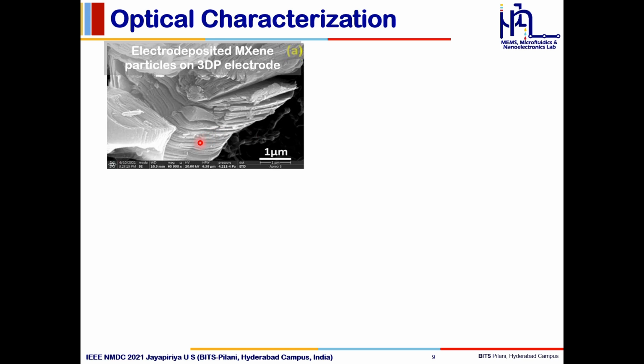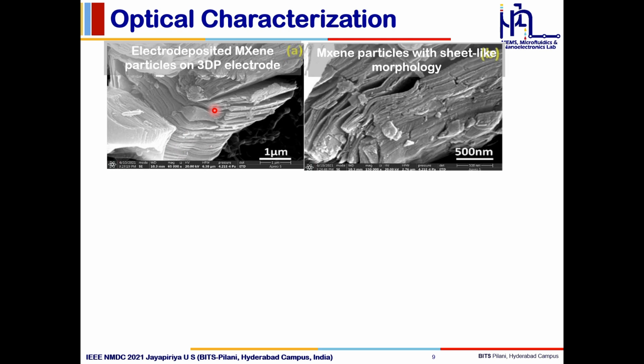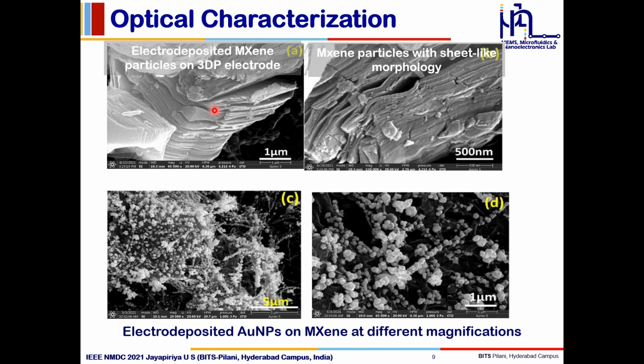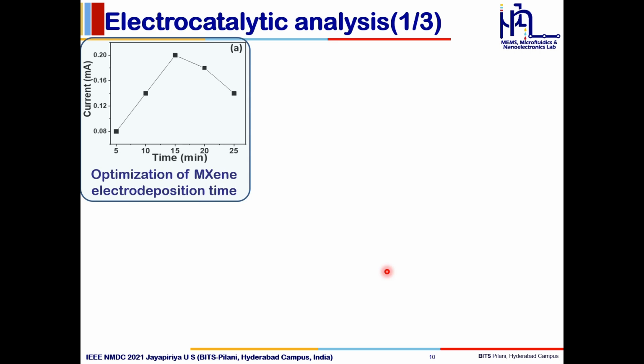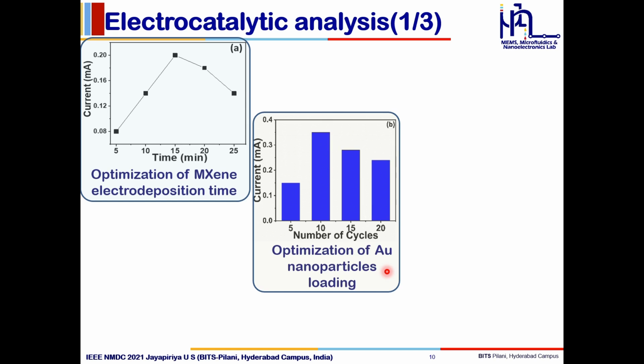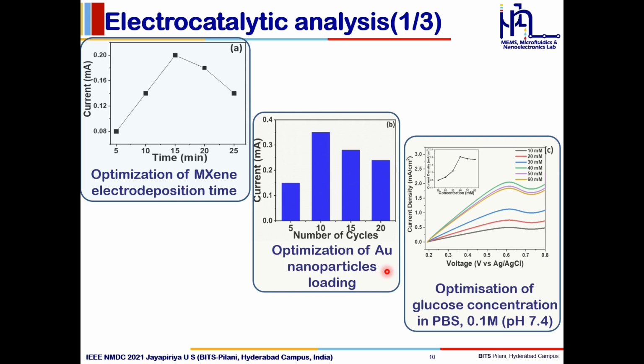To confirm the efficient electrodeposition on the 3D printed electrodes, scanning electron microscopy was done. It can be seen that the multi-layered MXene has been uniformly deposited over the 3D printed electrode, retaining its layered structure. Over this, the electrodeposition of gold nanoparticles has been successful, which is implied from these figures where gold nanoparticles are uniformly distributed over the MXene coated 3D printed electrodes. Further, electrocatalytic analyses were done to optimize the parameters for electrodeposition and the catalytic activities for the glucose biofuel cell.